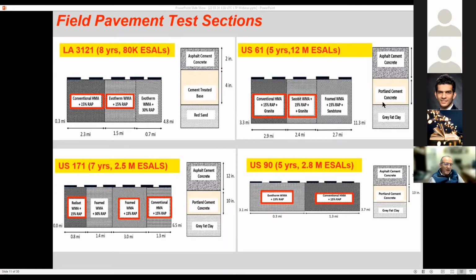So that might yield some issues, as you could see in the results, because it's not really a material issue. If you have a problem underneath in the composite, which is the PCC or the cement treated base, that's going to reflect on the surface performance. So keep that in mind. If we see anomalies, that's not necessarily due to the additives, it's probably due to something underneath.